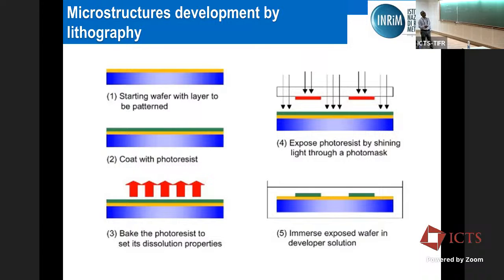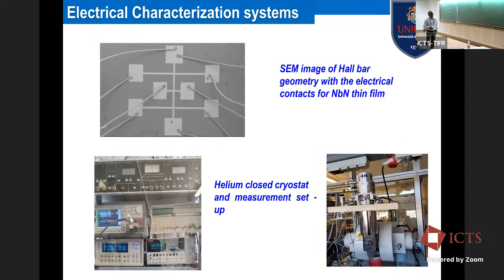So this is the process, basically, how we develop those structures. Right, we are making some kind of mask. So we deposit this photoresist onto the wafer, and after deposition, we expose it with the mask. Then we bake our photoresist, and after exposure, we develop this mask and develop this kind of a structure. Whatever kind of structure you want to develop, we can have those kinds of masks. For example, this is the Hall bar geometry which Meenakshi has developed for the IV characteristic measurements, right? And these are the electrical transport measurement systems, where she has measured all those IV characteristics and transition temperature. You can cool this up to 4 Kelvin, and this magnet of 1 Tesla is there, where they have done the measurements under a magnetic field of some millitesla.